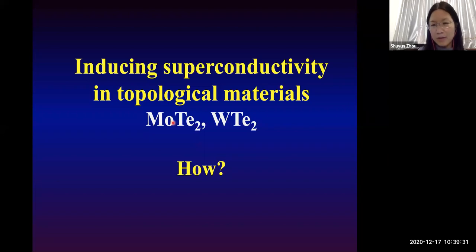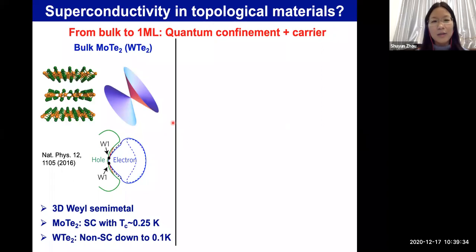So how can we induce superconductivity? Let's first look at the properties of this material, molybdenum ditelluride, from the bulk crystal to monolayer film. For this layered material, the electronic structure is strongly dependent on the sample thickness. For bulk molybdenum ditelluride, we know that it's a three-dimensional material, in particular a three-dimensional Weyl semimetal. Regarding the superconducting property, molybdenum ditelluride is a superconductor, but with a very low transition temperature of 0.25 Kelvin.